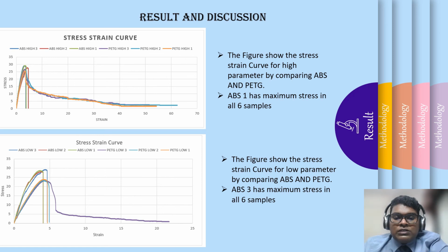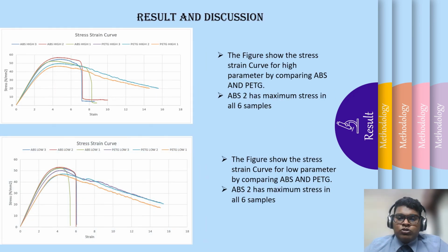The figure on the left shows the stress-strain curve for the high parameter by comparing all 6 specimens for ABS and PETG. From the stress-strain curve, we found out that ABS1 has the maximum stress, while for the low parameter, ABS3 has the maximum stress in all 6 samples. The figure on the left shows the stress-strain curve for the high parameter by comparing ABS and PETG. ABS2 has the maximum stress in all 6 samples, while for the low parameter, comparing ABS and PETG, ABS2 has the maximum stress.